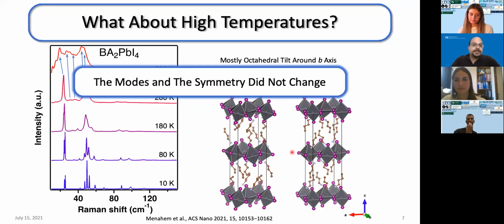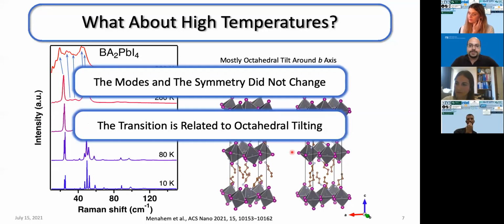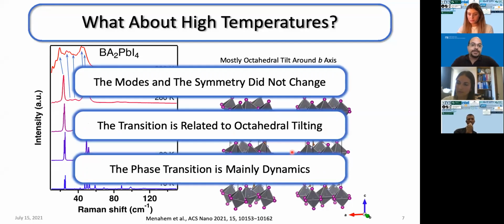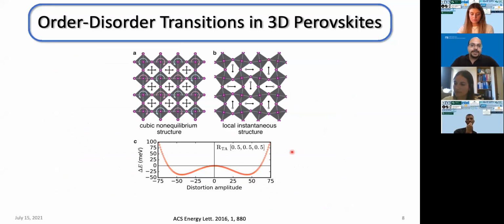So we see that the modes and the symmetries did not change much during the phase transition. The phase transition is related to octahedral tilting, and the phase transition is mainly dynamic. So we want to understand the phase transition of 2D perovskites in the context of 3D perovskites, what we already know on methylammonium lead iodide. So let's talk a moment, very briefly, on the phase transition of methylammonium lead iodide.